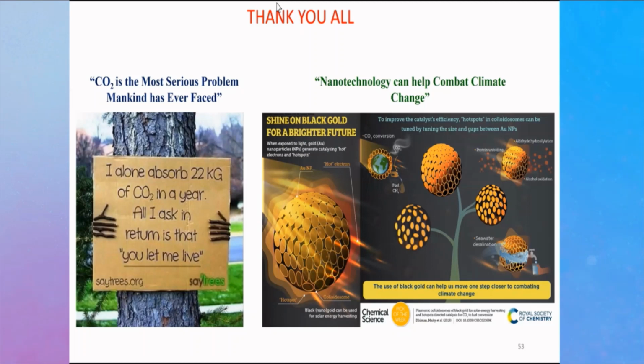Varad asked the question, how can we ensure that all gold nanoparticles will be of the same size after the nucleation growth method? Most of the time, if you really want monodispersed gold nanoparticles, which was not the case in our work, you use a coating agent, and there is something called burst nucleation, where you create lots of nuclei and have a quick growth. So ideally, you get monodispersed, similar-sized nanoparticles.